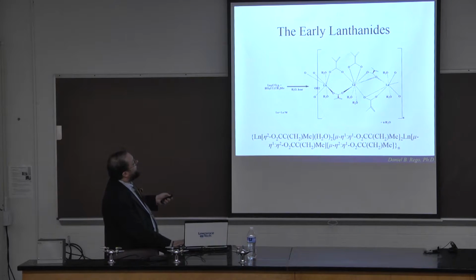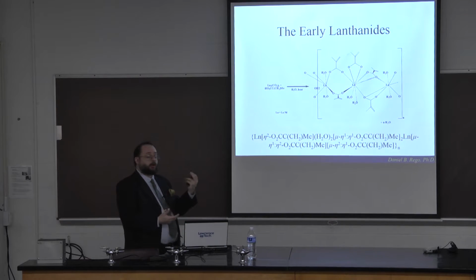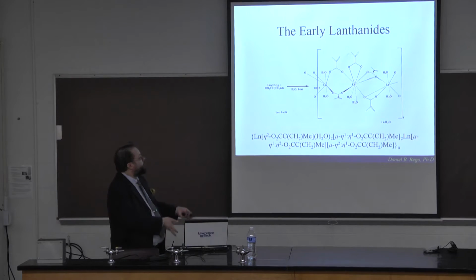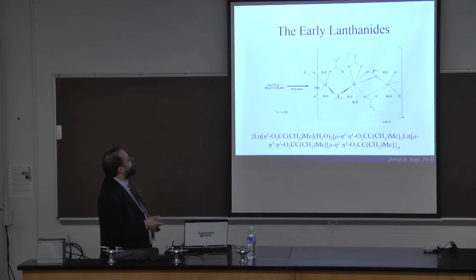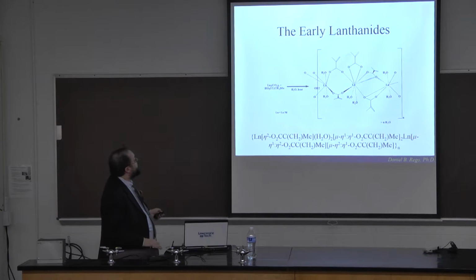So basically, I form these infinite chains of lanthanide methacrylates. And I do this by adding the acid in water directly to a lanthanide carbonate. So basically, it reacts like vinegar and baking soda. Releases CO2, water, no other byproduct, very nice and clean.